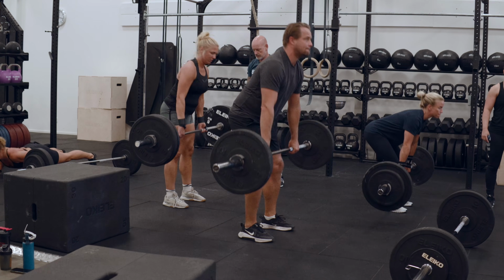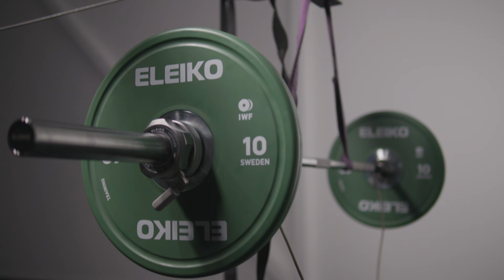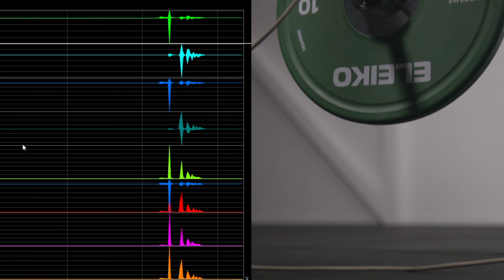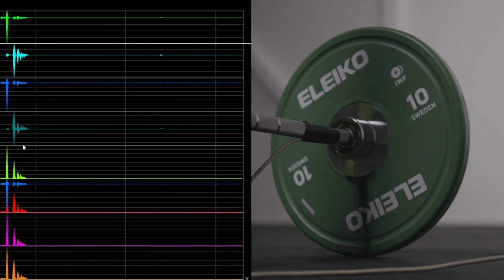These bars benefit the most from the improved fatigue resistance because of how they're used. Higher volumes of use overall in commercial facilities, and in particular more drops with thin plates in CrossFit or functional fitness type training. So to measure fatigue tolerance, bars are dropped loaded with a pair of 10 kilo plates and collars dropped from 2.2 meters onto 30 mm rubber flooring to determine the forces from the impact that are acting on the bar. With these sleeve design changes, those forces are reduced to below the so-called threshold of eternal life. This effectively means that the forces don't get high enough to stress the material to the breaking point, even with repeated use over time.